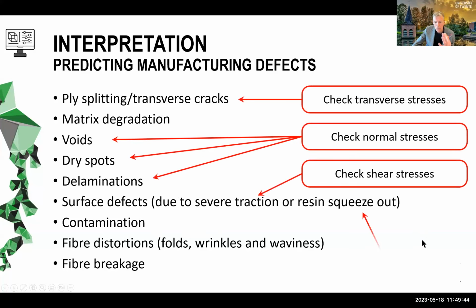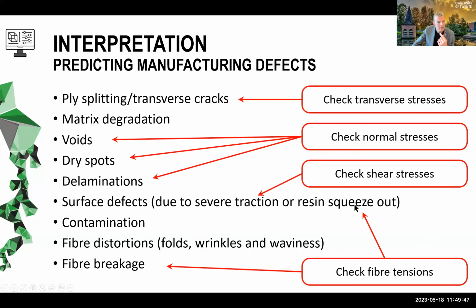If we just look at what the simulations bring us, then transverse stresses will relate to this defect. Voids, dry spots, and delaminations will relate to the normal stresses during our forming simulation. Surface defects, well, we can have a look at the shear stresses in our contact elements. The fiber tensions will have an effect on resin squeeze out and fiber breakage. And that practically only leaves us with fiber distortions, folds, wrinkles, and waviness, the thing I started with, if you remember from my second slide.